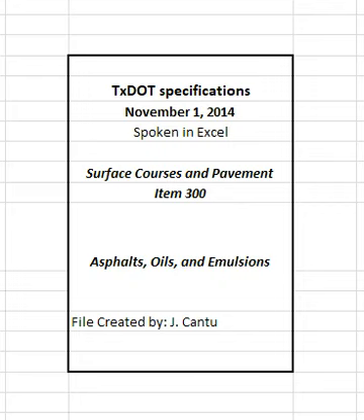9.5 to 12.7 millimeters, wide, square end metal spatula to bring the material on the bottom of the cup to the surface, i.e., turn the material over, before passing the test flame over the cup. Start at one side of the thermometer, move around to the other, and then return to the starting point using 8 to 10 rapid circular strokes. Accomplish agitation in 3 to 4 seconds. Pass the test flame over the cup immediately after stirring is completed.